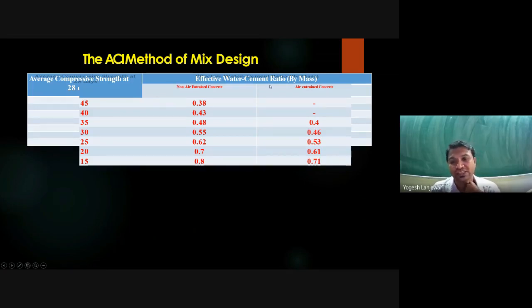Here the effective water cement ratio is divided into two parts. The first one is for non-air entrained concrete and the second one is for air entrained concrete. For the first two grades, that is M45 and M40, it is the same, that is 0.38 and 0.43. But if we go to M35, the water cement ratio changes. For non-air entrained it is 0.48 and for air entrained it is 0.4.